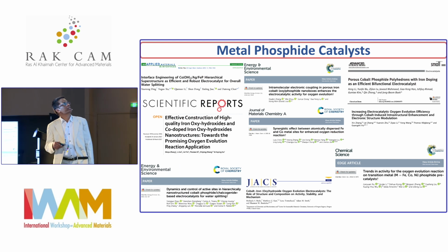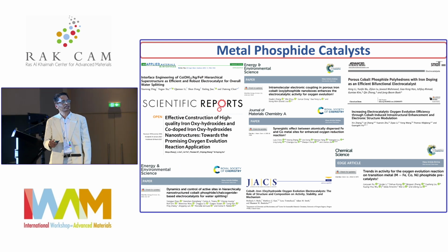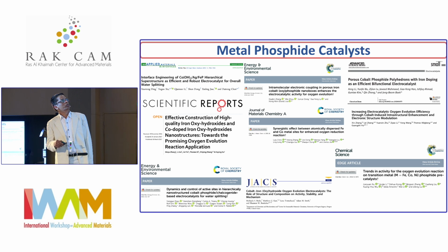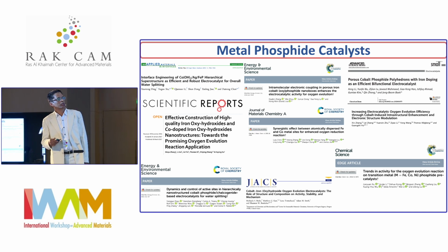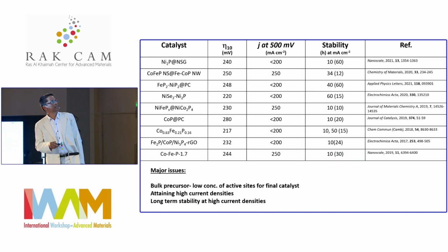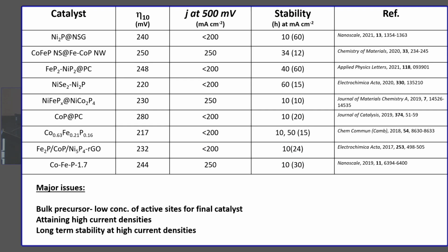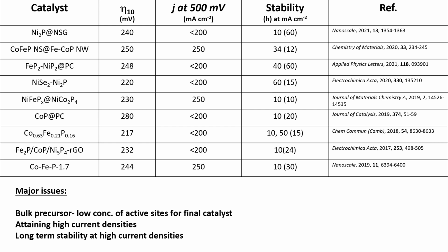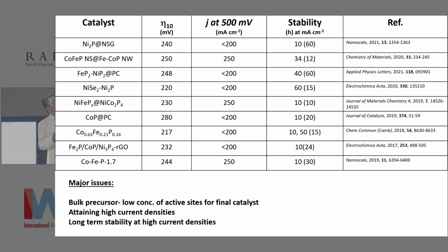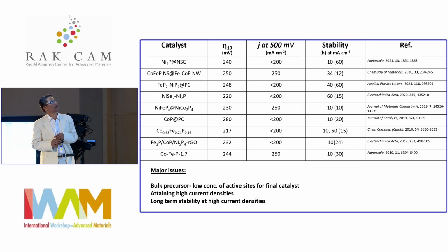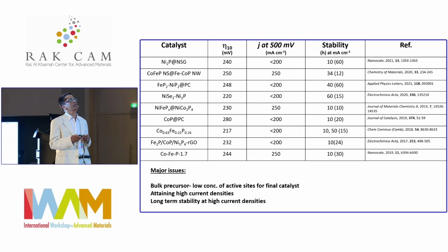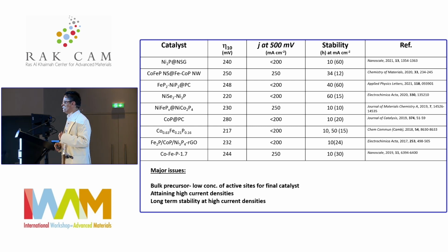And as I said, phosphides have received a lot of attention in recent years. Many people use cobalt and iron phosphide and nickel phosphide, and so on. But in all the cases there is still the overpotential problem: to reach even 10 milliampere per centimeter square current density, you have to live with more than 200 millivolt overpotential. Even if you go a little higher, to 500 millivolt overpotential, the current density is very low.